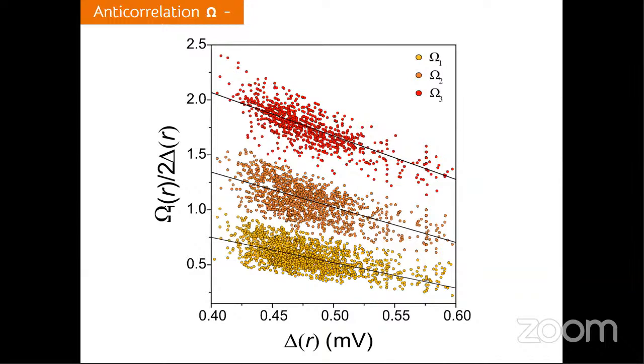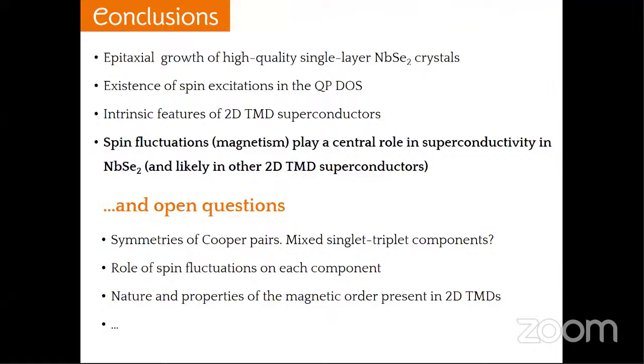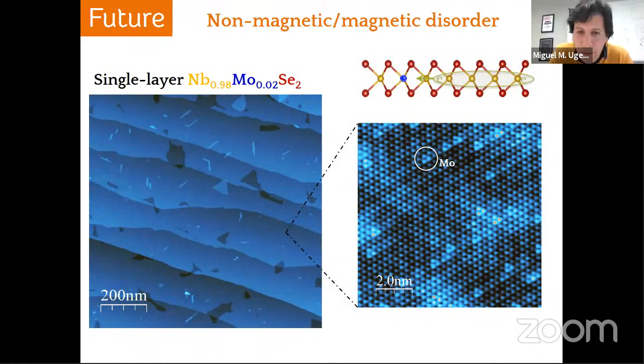Okay, so at some point I was going to ask whether at some impurities, not necessarily magnetic or non-magnetic, you have observed some kind of local state? I will tell you in a couple of weeks, because this is a fresh result. We were just able to image these molybdenum atoms. We are trying to decrease the number of molybdenum atoms to get them even more isolated. We do observe the emergence of a flat band at around minus 0.5 millielectron volts, but far from the Fermi level. So we don't know exactly if there will be a clear effect on superconductivity, but I'll be happy to